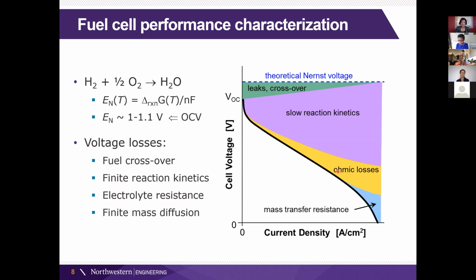We're interested, of course, in the power, and the power is just the voltage multiplied by the current. So the power density is voltage times the current density, and it gives us a curve that looks something like that shown here. Typically, we operate at around 0.7 volts, which gives us a good balance of efficiency. The higher the voltage, the better the efficiency, and we get a reasonable power density. Of course, you could have very high efficiency if you're not actually using much of your fuel, if you're up here. And if you're operating at very high power, your efficiency will be low.